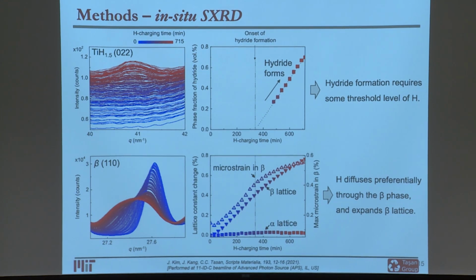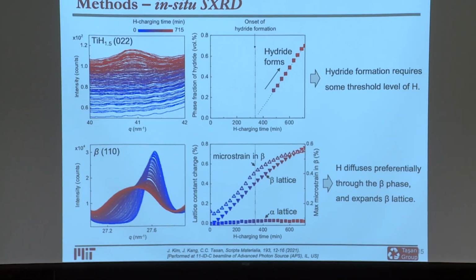There is no hydride yet, and once hydride starts forming, you can see that actually some of these strains are compensated or going in the other direction. And you can see that these strains are much more significant in the beta phase than the alpha phase. So although you don't see something directly, you are getting information about where hydrogen is going and transferred in the material. So that's one technique. But you want to learn more.